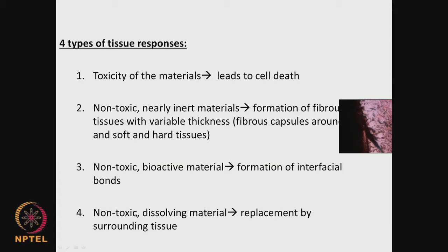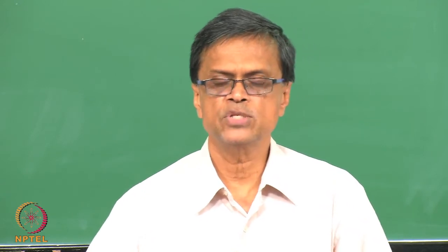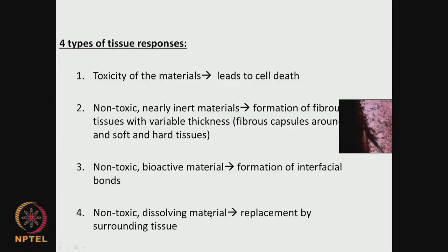We may say non-toxic dissolving, but there could also be toxic dissolving materials. For example, polylactic acid is dissolving or bioresorbing, but the lactic acid produced is a little bit toxic — there could be some cells dying in the vicinity due to local acidity. We have different situations and the tissue responds in different ways.